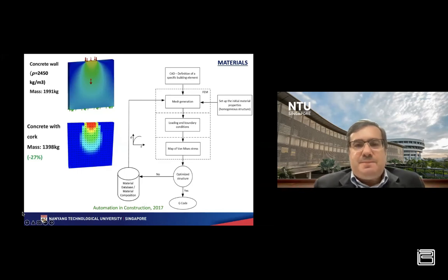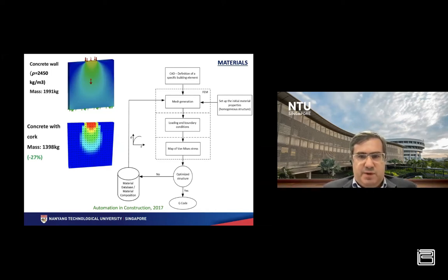Okay, yeah. Well, also in terms of materials, this was a project that I had with colleagues at Penn State and at the Polytechnic Institute of Leiria. We tried to develop a strategy to create functional graded materials. Basically, the initial idea was to develop a strategy to print these functional graded materials, allowing in real time to change the concrete composition to reduce the amount of concrete in low-loaded areas and replace concrete by a mixture of concrete with cork or expanded clay. And these were the initial materials.